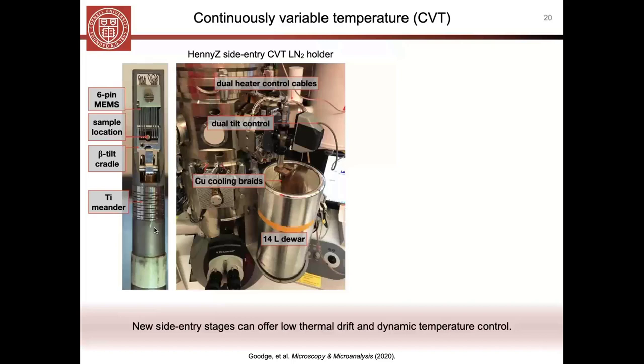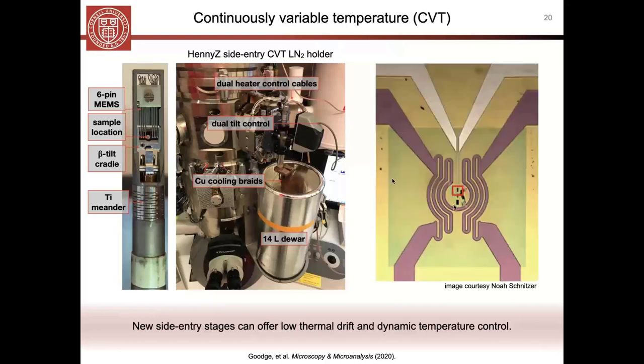And so using liquid nitrogen, we cool this holder down to a baseline temperature around 100 Kelvin. And then we have a 6-pin MEMS control, which you can see here, where you can zoom in. We mount our sample on a MEMS chip that looks like this, and we can control with these four leads the heating coils. This is a very local heating coil here. And so what that allows us to do is to cool the sample down to a cryogenic baseline, and then we can dial in exactly whatever temperature we want anywhere above that.